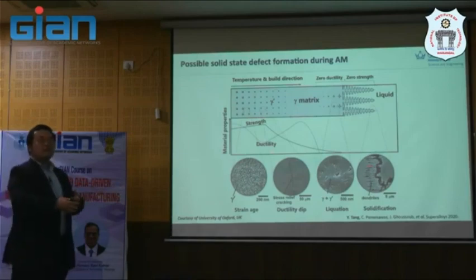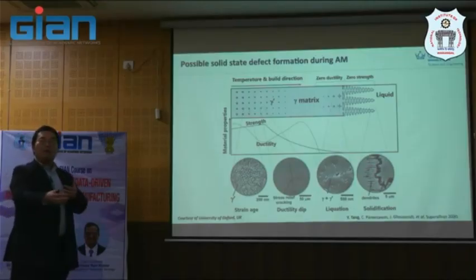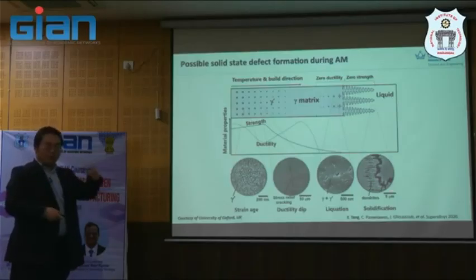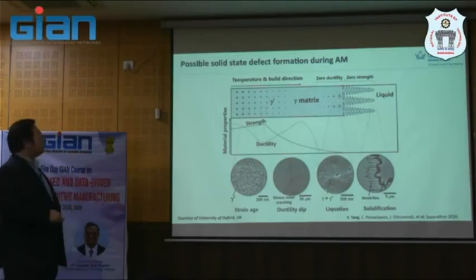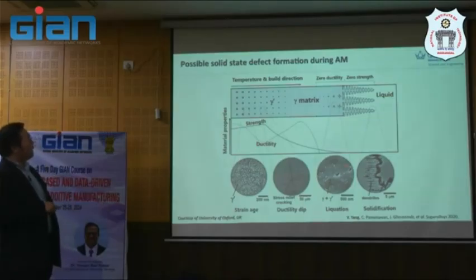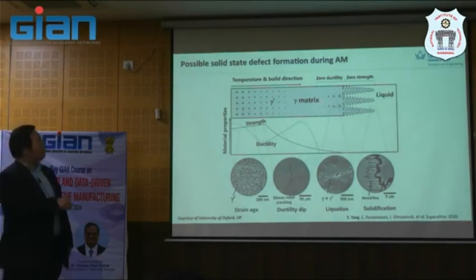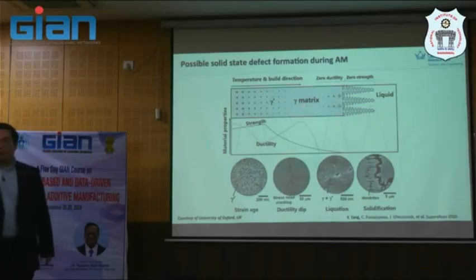It's near completion of the solidification, but it's actually tailing off, probably due to other factors like another mechanical profile surrounding that, or due to the geometry, residual stress induced or whatsoever. But if we conceptually draw the strength and ductility profile here, the strength will be good when you have quite homogeneous structure, but it will drop significantly, or this defect will make it drop significantly, and it's the same as ductility. Good when you have homogeneous structure, drop, and rapidly recover back at the matrix. It's a pure nickel FCC here, and then drop again when the defect kicks in.